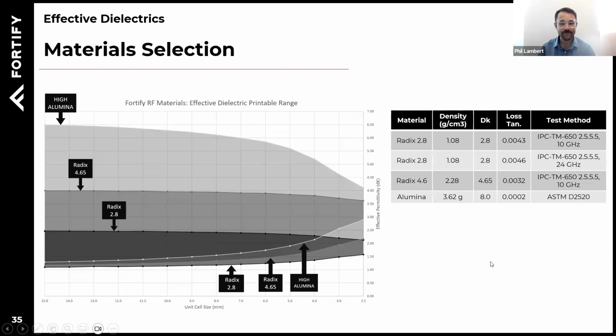And so how to digest all this? We created this material selection guide to help you understand what effective dielectrics are available to you across which materials, depending on unit cell size. So the way that you do this is you determine in your application, what frequency am I trying to design my lens for? Okay, it's maybe 40 gigahertz, 35 gigahertz. You say, okay, which materials do I need? What kind of dielectric constant range do I need in order to accomplish my design? You'd say, okay, I can do it in just 2.8. So you then come over here, you'd say, okay, I know I can use a 5 millimeter unit cell. And on my y-axis here, I have effective permittivity. We can go from about 1.2 up to 2 point something, 2.4 probably. And that's how you'd read that.